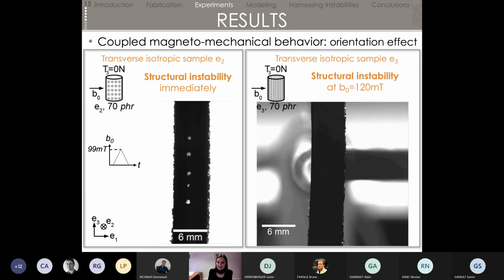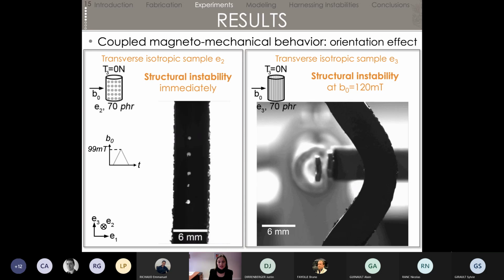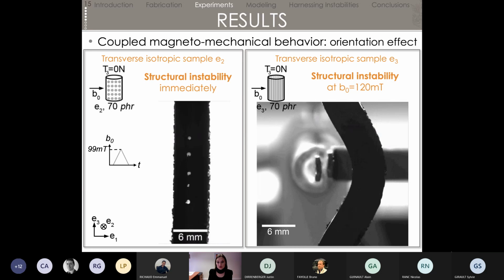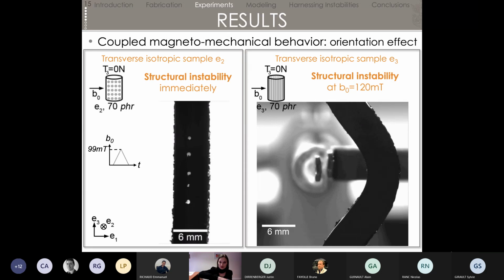Same problem that we had when the chains are again perpendicular to the magnetic field, but this time in the plane of our screen. The whole sample wants to turn to align itself with the magnetic field. But because here we have the heads of the sample attached at the top and bottom, that gives us this bending. So we observe again that we do not measure any magnetostriction, so no strains induced by the magnetic field, but instead large instabilities and samples that we cannot control.